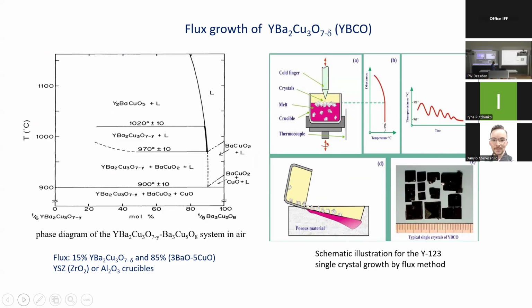Here is how we could separate crystals from the melt. It's like decanting inside the hot furnace. Here it's called the cold finger approach. Cold finger is very simple. It's just a ceramic air-cooled tube. And using this cold finger, you just localize the crystallization on the melt surface. So it's much easier to detach or cleave crystals from the surface. And here are typical YBCO crystals grown by flux in ceramic crucibles, either aluminum oxide or yttrium stabilized zirconium oxide. They are quite large in the ab plane, but relatively thin along the c-axis, normally up to half a millimeter.